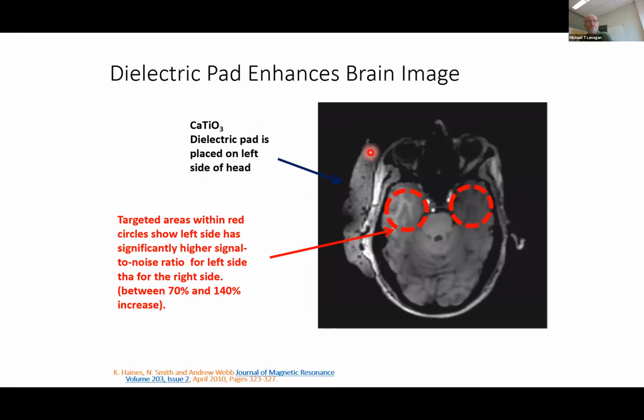Some of the first experiments that were done at the University of Leiden in collaboration with Penn State shows this effect. So here in this case, we have this pad shown here, and we don't see the coil. And on the other side, we actually have a water pad that's not really shown. It's actually deuterium. And what we're doing is comparing the signal strength in these two different regions. And what we can see is the signal strength with this pad increases about a factor of 2, somewhere between 70 and 140%. And this work was done by Andrew Webb about a decade ago. We supplied the materials, and it really generated a lot of interest in this coupling of the signal in and out to really increase the signal to noise ratio. So a lot of work since then.